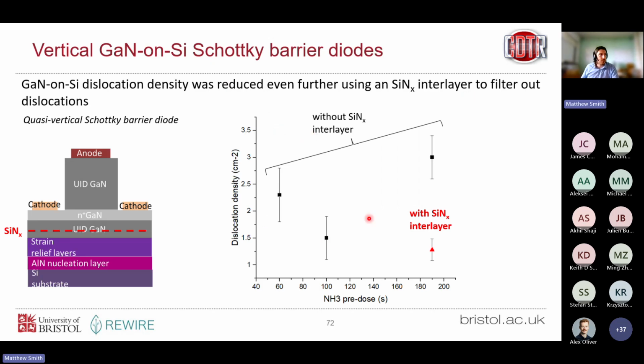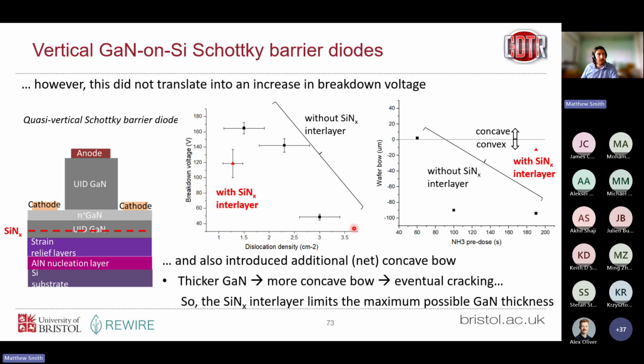So that breakdown voltage effect, dislocation density isn't the full story. What we do find is that there are some outliers, and we also have to consider wafer bow. So this story isn't fully told. I think we still have some more investigations to do here on the relationship between dislocation density, breakdown voltage, growth conditions before we can fully understand this. But we're currently fabricating devices which we hope are going to shed some light on that.